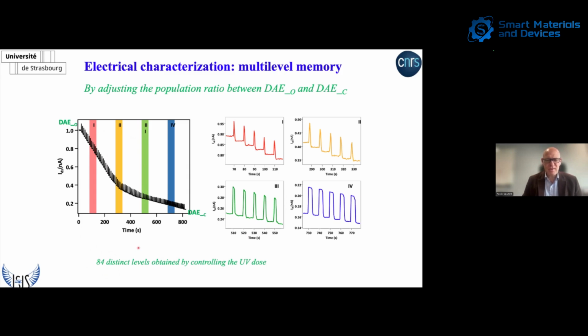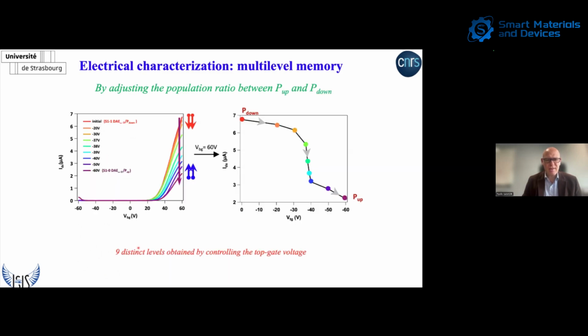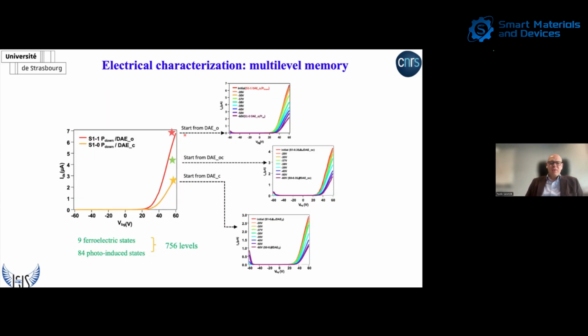Now, also, as I mentioned, the application of a voltage allows you to have a total or also a partial orientation of the dipoles. And this has been used in order to observe 9 different levels that can be controlled by electrical stimuli. And so if you sum up these two types of stimuli, you can have 9 level states that derive from the ferroelectric material, 84 from the photo-controlled one. And so that allows you to fabricate 9-bit memories, which can be increased up to 11-bit memories if you use a fast laser.